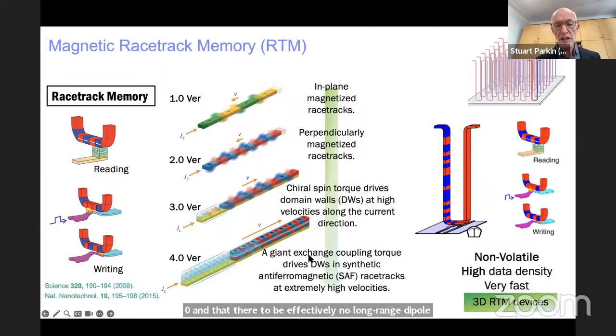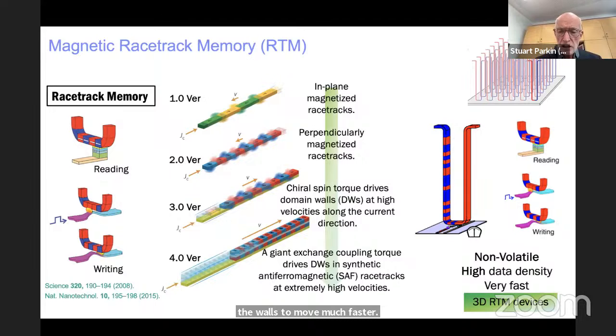And it turns out that we discovered that this antiferromagnetic coupling field itself gives rise to this giant exchange coupling torque, only possible in these synthetic antiferromagnets. So then the domain walls move several times faster, at speeds of about 1 kilometer per second. Very fast, and that's fast enough to make very, very interesting racetracks. In fact, you probably don't want the walls to move much faster. So this is fantastic and makes racetrack basically possible.